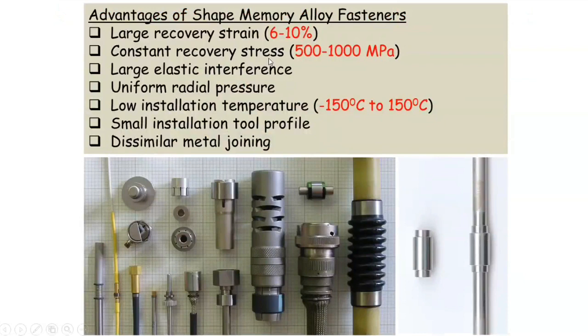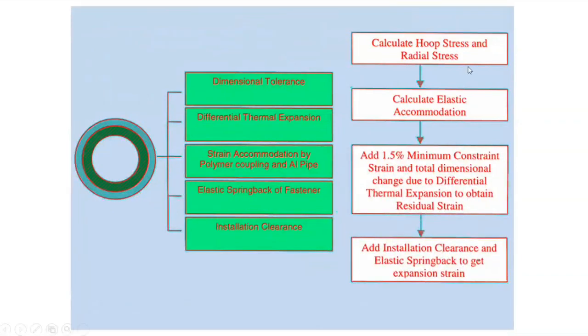Just to summarize some of the advantages of fasteners: you have a large recovery strain. We have said that it's a constant recovery stress, finite, and you see the plateau in the stress-induced martensite. That's the constant recovery stress. It's like a bangle, so you can sort of do anything to it. You have a uniform radial pressure on account of it. It can wrap itself around the object, and you have a low installation temperature, much less than 150 degrees. You have a low installation tool, hardly any profile, just a tweezer or something like that. Of course, you can apply it to dissimilar metal joints.